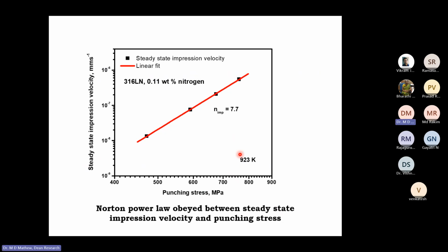This shows the correlation between steady state impression velocity and punching stress. On a log-log plot, you find that there's a linear relationship, which is very similar to the Norton law. And the slope is equal to 7.7, which is the so-called stress exponent. And that is the number that we expect from a standard uniaxial creep test, a value of n in this range at this temperature. So the Norton power law is obeyed between steady state impression velocity and the punching stress.